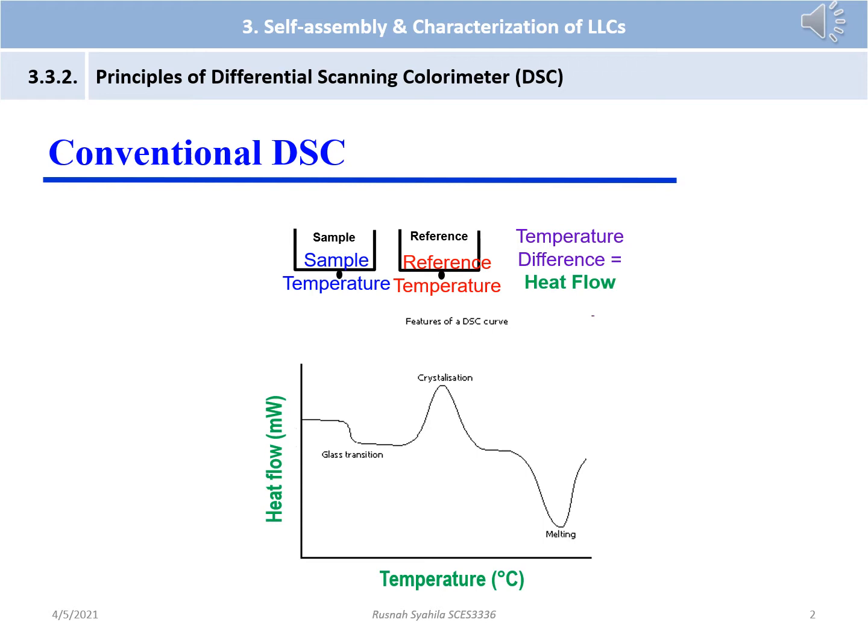DSC is more accurate for assigning the transition temperature and confirming the phase change, but gives no information on the type of phases. Except, it is very useful to distinguish gel phases from crystals. Typically, the delta enthalpy for gel melting is almost half of the delta enthalpy of crystal melting. Gel phase usually melts to lamellar but not always. Mesophase melting transition enthalpies are small, typically 10% of the delta enthalpy of crystal melting. Based on the enthalpy change value, there is no difference between lamellar, hexagonal, or cubic phases.